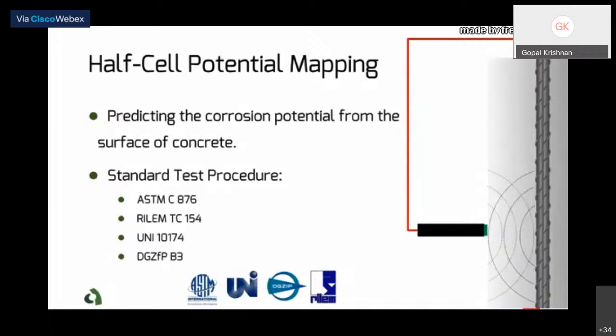The half-cell test can be used to predict the corrosion potential from the surface of concrete. Several associations have standardized the test procedure, including ASTM, UNI, and RILEM. In the half-cell potential method, the potential values at the surface of concrete are measured with respect to a reference point. Concrete surface should be prepared before doing the test, that is to remove paint or other non-conductive layers from the surface. The surface should have a minimum amount of moisture. A sound electrical connection should be established between the reference electrode and reinforcement.